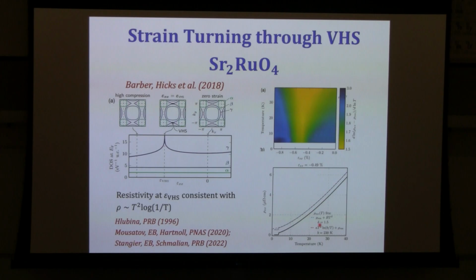So this is, if you like, a trivial example of strange metal behavior, not of the most exotic type. It's not the strongest deviation from T squared. It's just T squared log T that you can really understand almost quantitatively. And there's really nothing exotic going on. You just need to understand where this extra pileup of low energy states is coming from.